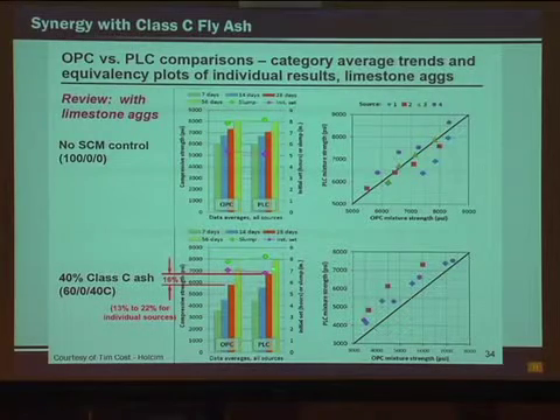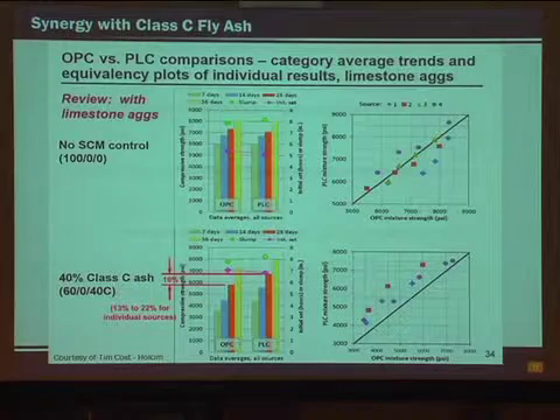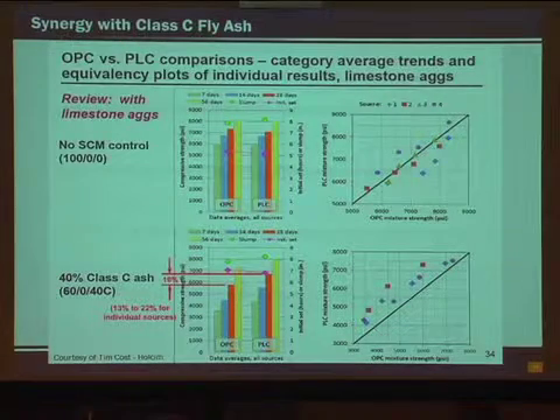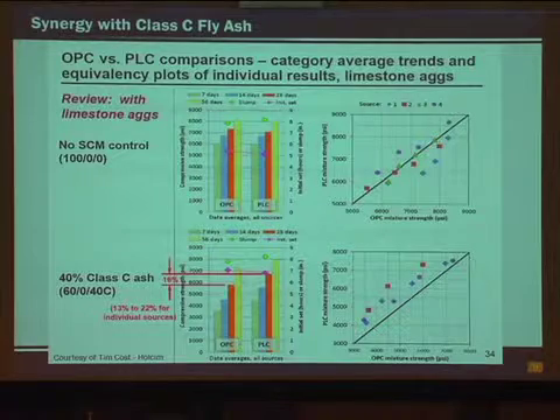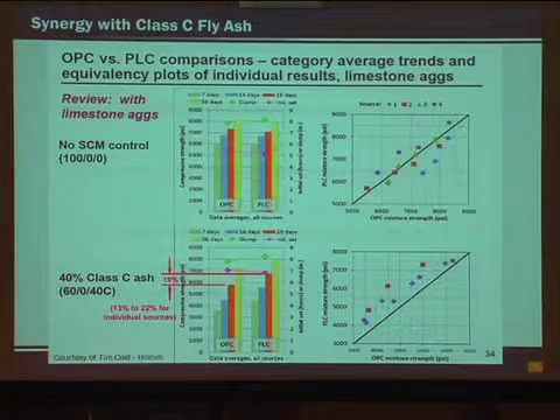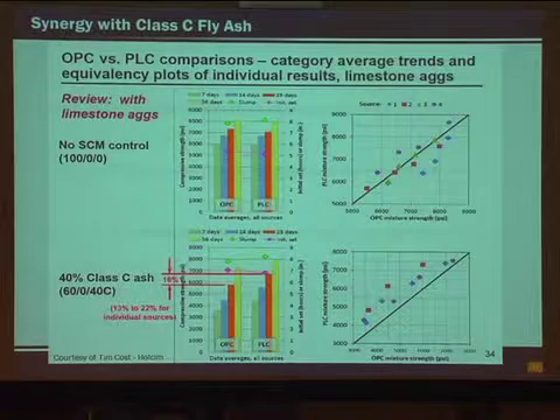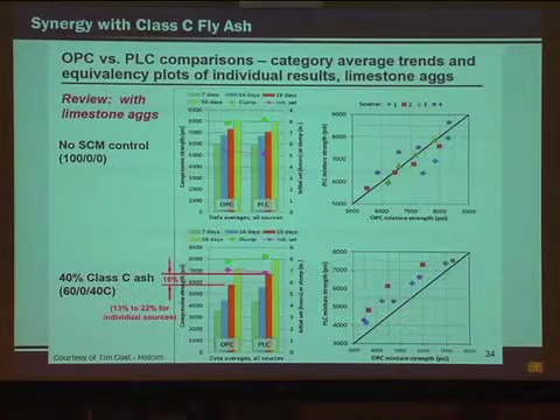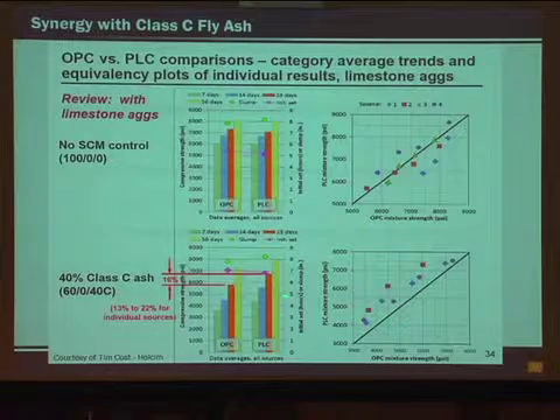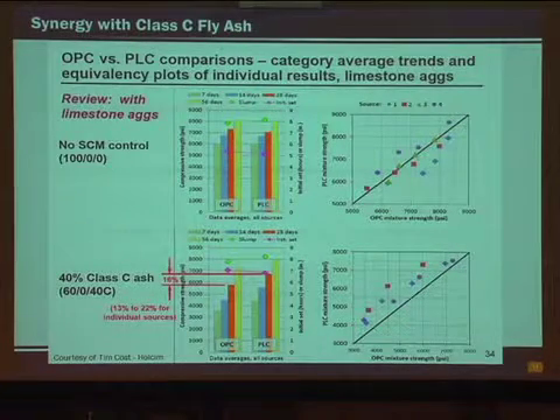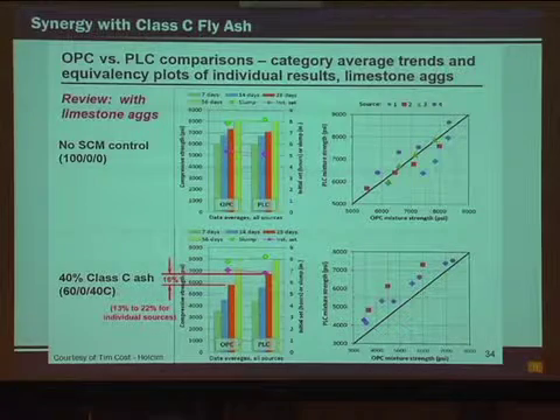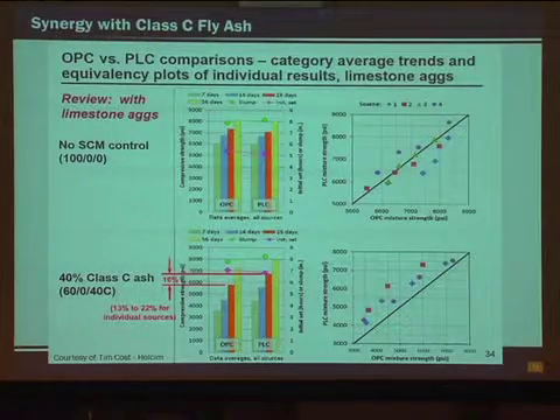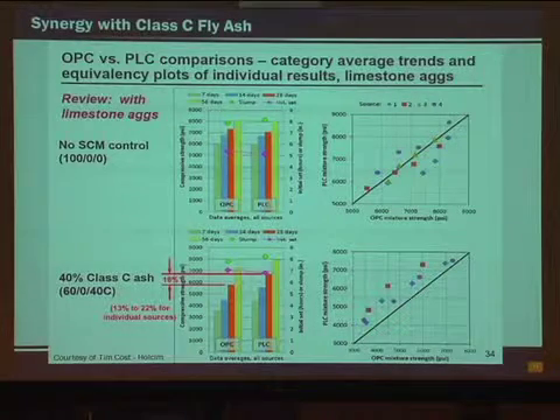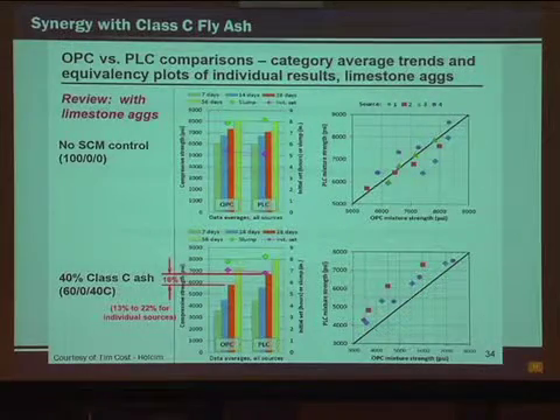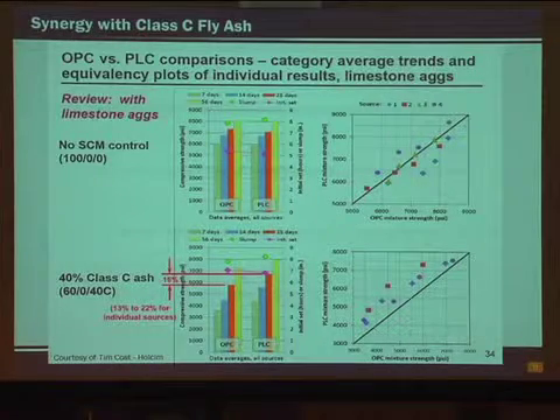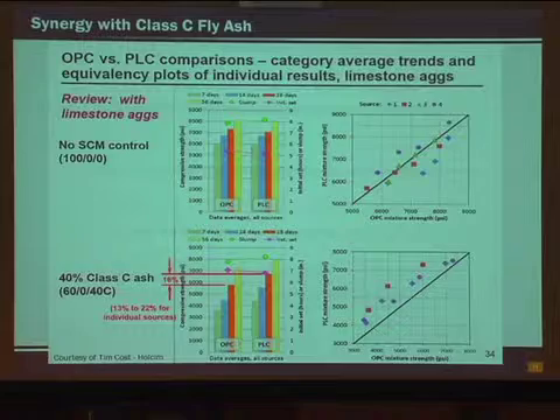Now, one of the thoughts is that because Class C fly ashes are calcium aluminate based chemistry, again, the limestones will react with that aluminate phase in cement, so the same should go for reacting with that aluminate phase in fly ash. And so Class C fly ash has that aluminate component, and so you tend to see this strength increase. You don't see the same strength increase with Class F fly ash because it doesn't have as much aluminate phase as the C ash. So this could be a significant benefit when we're looking at fly ash replacements and things like that.